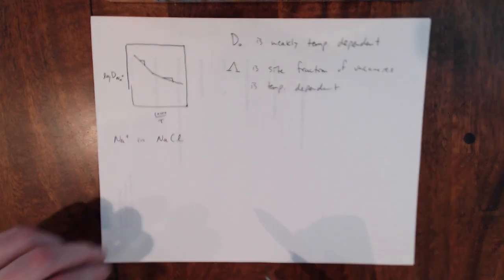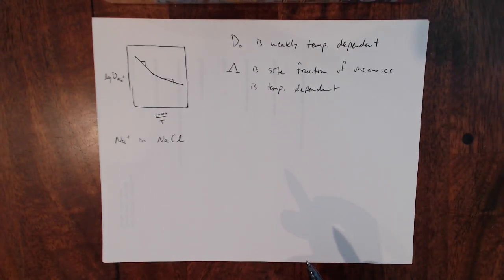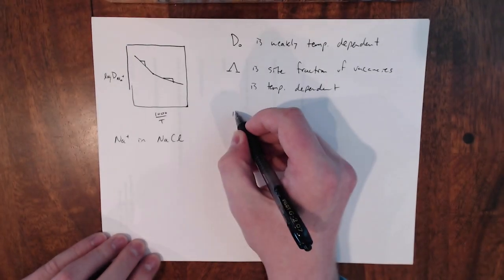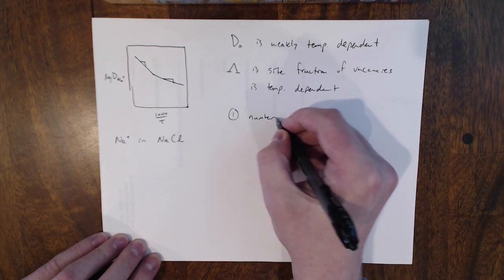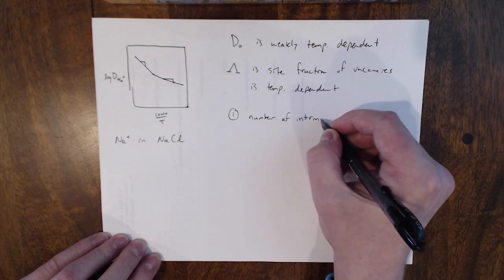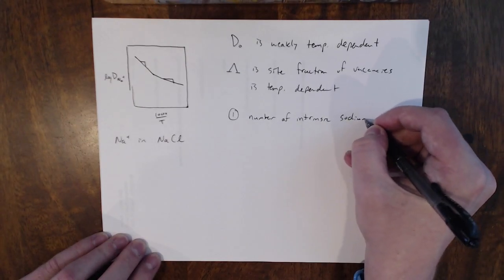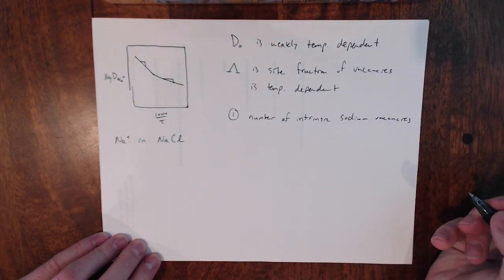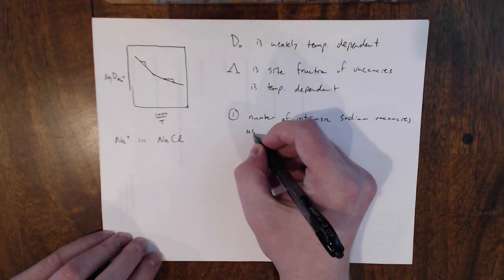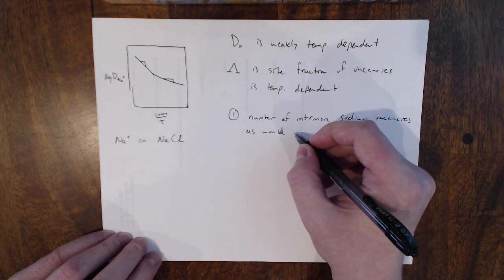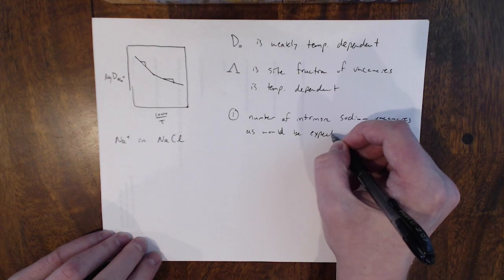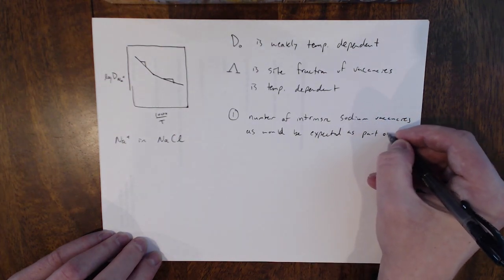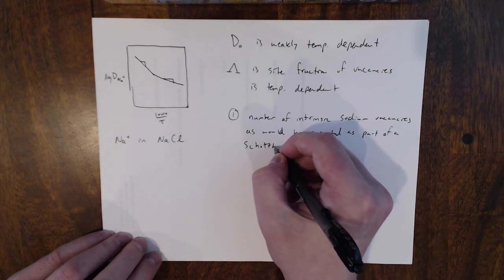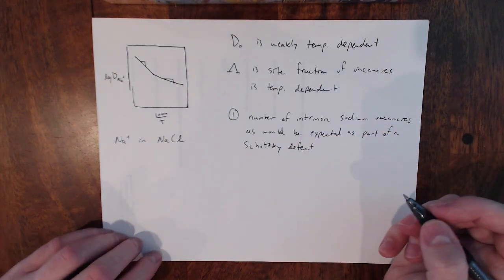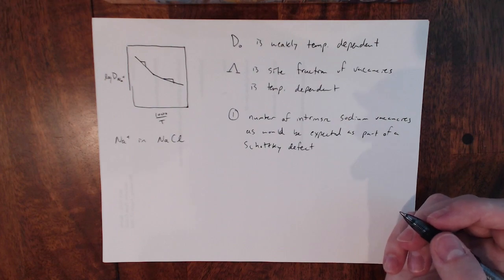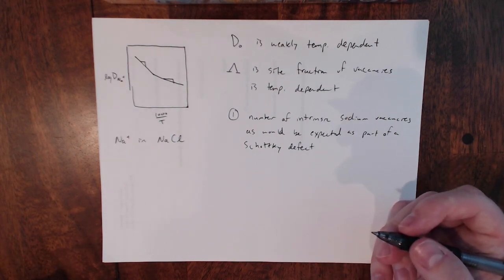All right. So in this specific case that we're looking at, we want to look at the diffusivity of sodium ions. So it can be controlled by two things. One, the number of intrinsic sodium vacancies, right? So this would be expected in a Schottky reaction. So if we have a Schottky defect, we would expect these types of vacancy. And so that will be thermally activated, and so that can affect what we have.